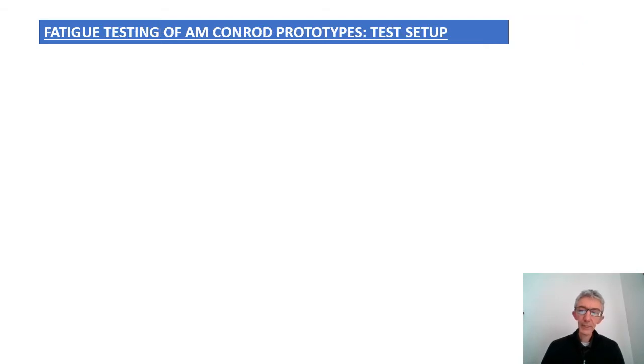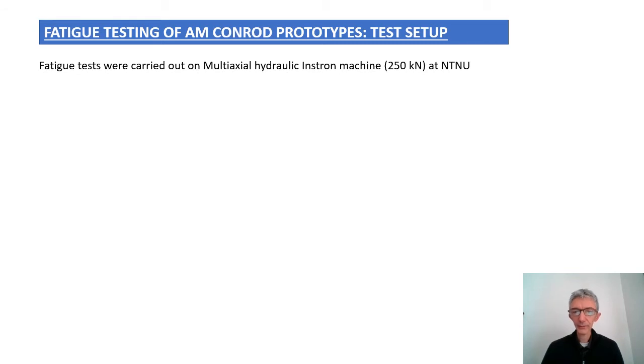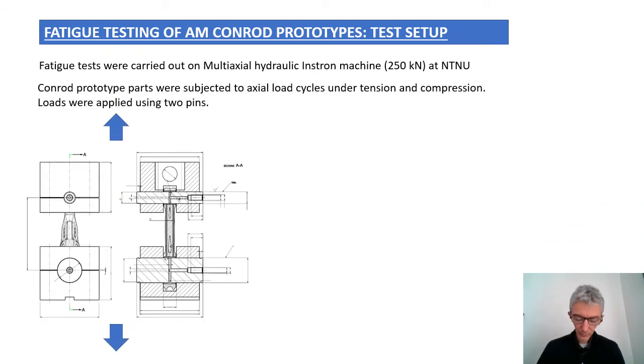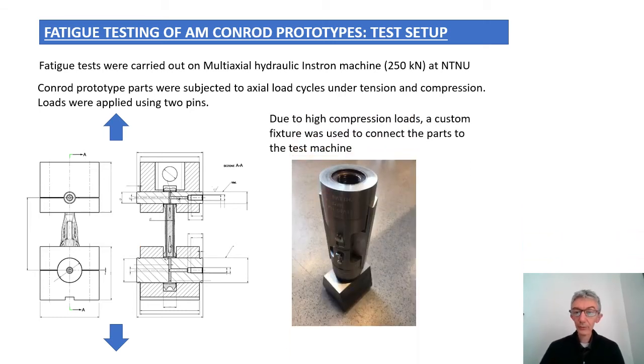Now, having a few prototypes available, some fatigue tests were then carried out, and in particular, these were carried out in the laboratories of NTNU, and the con rod prototypes were subjected to axial loads under tension and compression. The loads were transferred to the con rod using pins, and with this configuration, and due to the high compression loads that are expected, a custom fixture that was available in the laboratory was used to properly connect the parts to the test machine.